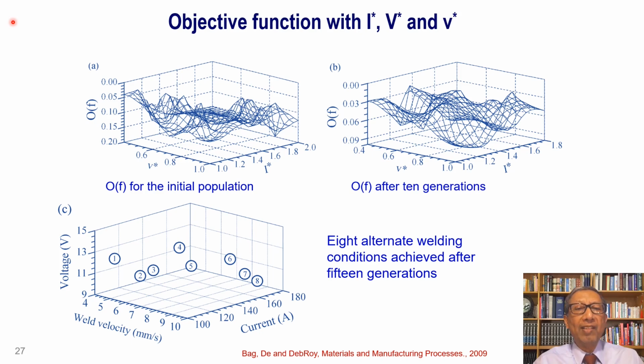We want to use a global search algorithm called a genetic algorithm, which adds and removes individual combinations of current, voltage, and scanning speed, and then recalculates the objective functions of the entire population. And after many of these iterations, we get 8 combinations of current, voltage, and scanning speed that would give us acceptable objective functions. That means acceptable values of current, voltage, and scanning speed that would result in low values of objective function. That means we are now getting for all of these combinations the right width of the fusion zone and the right depth of the fusion zone. And there are 8 alternative variables that can give us that.